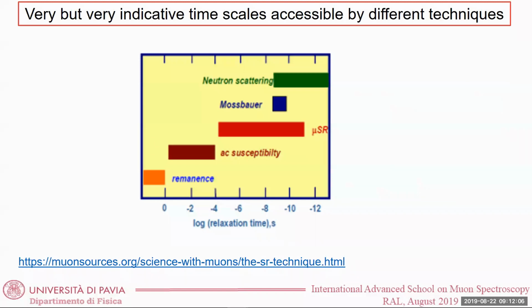But this should be taken with care because it's quite indicative, in the sense that with MUSR, in principle, depending on the type of experiment you want to do, you can probe even dynamics which are of the order of a second. You can probe dynamics which are even faster than 10 to the minus 12. And by the way, if we compare this to nuclear magnetic resonance, one would say, okay, where are we with nuclear magnetic resonance? In principle, you can probe all this range without big problems with the NMR.